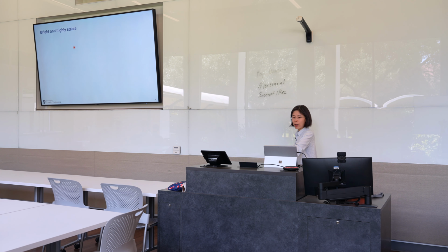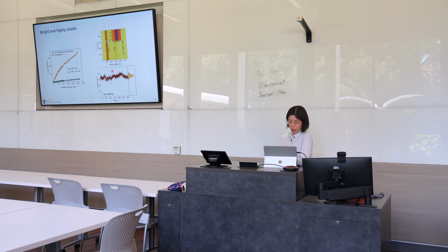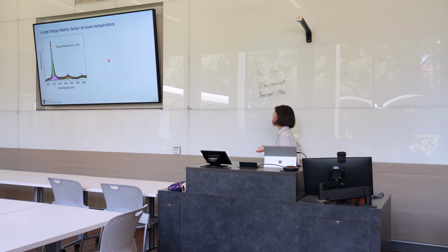Not only do we have a high single photon purity, but these emitters are also very bright and highly stable. We characterize the brightness of our emitter to be almost 500,000 counts per second. In addition, if you continuously excite the emitter for over 5 minutes, you do not see any blinking, and you do not see any wandering of the emission wavelengths. So this signifies the high stability of these single photon emitters. In addition, we realize our emitters have a high Debye-Waller factor. The Debye-Waller factor describes the percentage of photons emitted into the zero phonon line rather than the phonon sideband. So a high Debye-Waller factor is very important for achieving high brightness of single photon emitters.